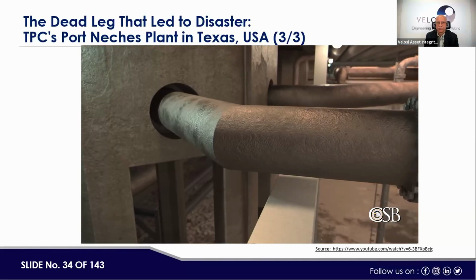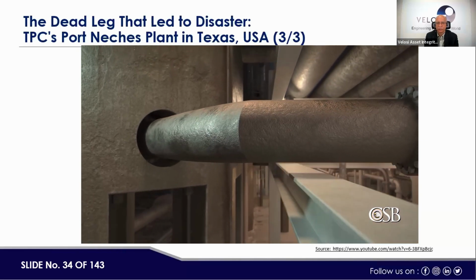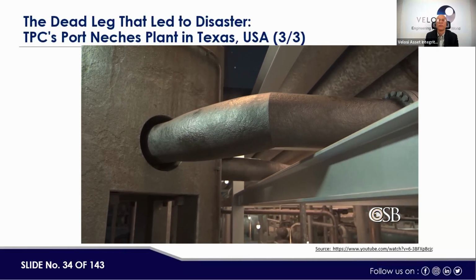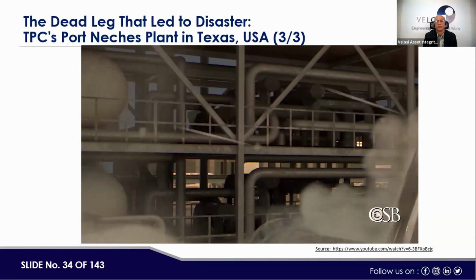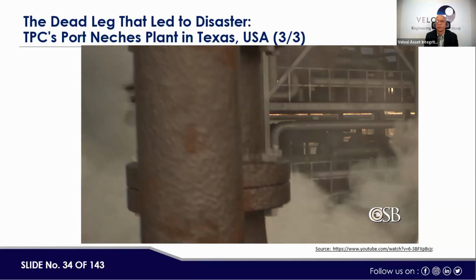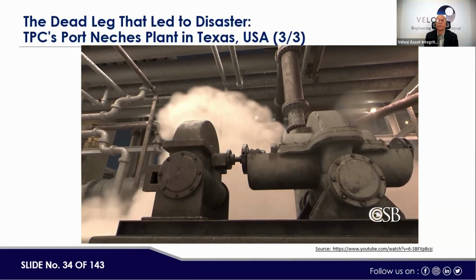At 12:54 a.m. on November 27th, excessive popcorn polymer buildup caused the dead leg piping to suddenly rupture. Approximately 6,000 gallons of liquid, primarily composed of butadiene, emptied through the ruptured piping in less than a minute. The liquid vaporized upon release to the atmosphere, forming a flammable cloud.